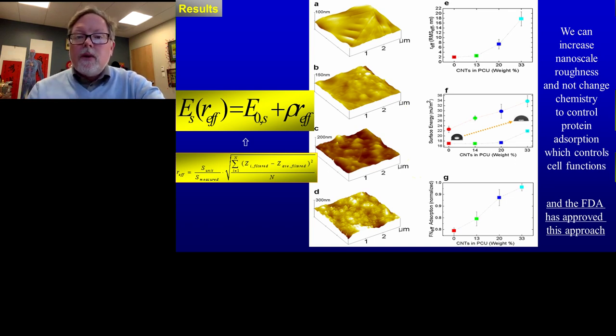We stopped at 33 weight percent, and you might ask why? Why did we stop at the nanoscale roughness we got when we added 33 weight percent of carbon nanotubes to polycarbonate urethane? The reason is the energy we got, as you can see in the graph again on F, the energy we got when using 33 weight percent is the same energy as mucin. So it gave us the same energy to enhance the absorption of a protein, mucin, that reduces bacteria attachment. And that's what's shown in G. It basically is an ELISA test, if you're familiar with that, to measure how much of a protein is absorbing to our surface. And we get the most mucin absorbing when we use 33 weight percent carbon nanotubes.